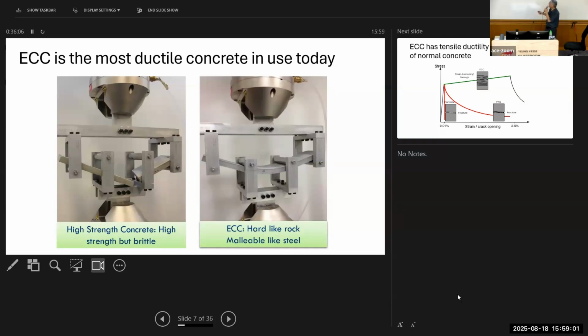If you look very carefully on the tensile side of this slab here, after it has been bent to this shape, you'll see micro cracks, very tiny micro cracks on the bottom side. So this is damage, okay? I have deliberately damaged the material by exerting an extreme loading to a very large deformation, and yet it did not break into two parts. Okay, it's still holding the load. So this is a good example of what I meant by damage tolerance. The material is damaged when it's under extreme load, but it still carries the load imposed on it.